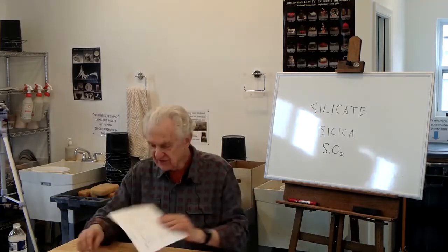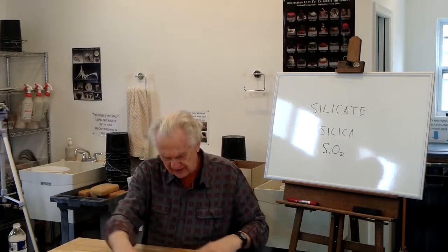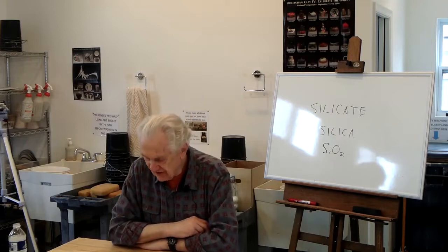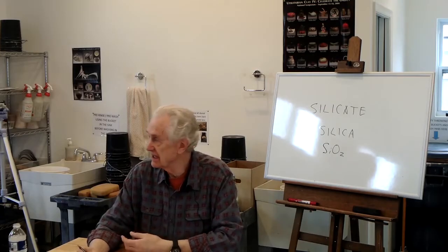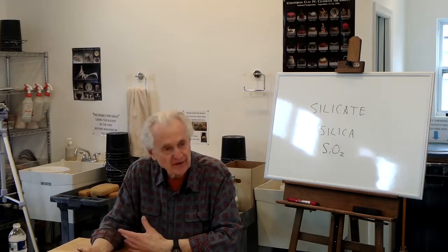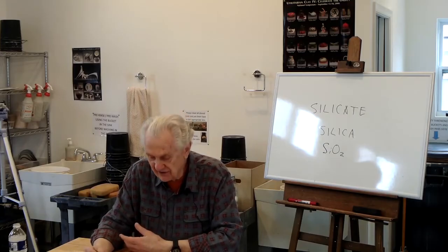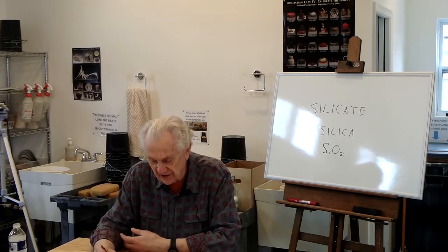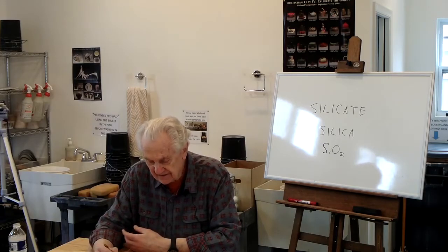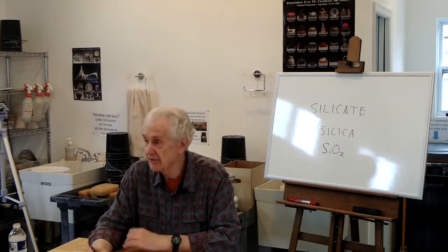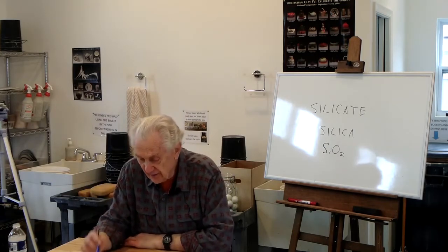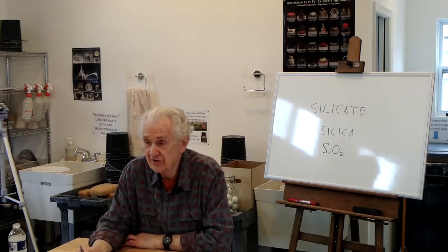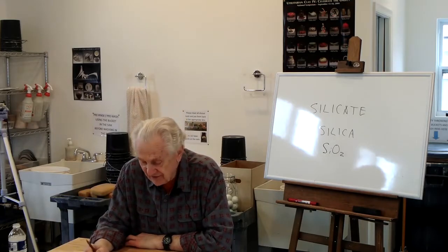When we talk about a glaze recipe, these are cone 10, they happen to be cone 10. This first one is for a celadon glaze, the classic Asian clear green glaze that you see in a lot of places. And when you see a recipe, this is typically what you may see, a list of ingredients. I've listed the names of them here: Custer Feldspar, whiting, EPK, Flint, and red iron oxide. And I've also just incidentally put down the chemical formula for them. The formula should be written as this. The W/O means weight percent, on the basis of weight. So this is the way you might see a recipe.